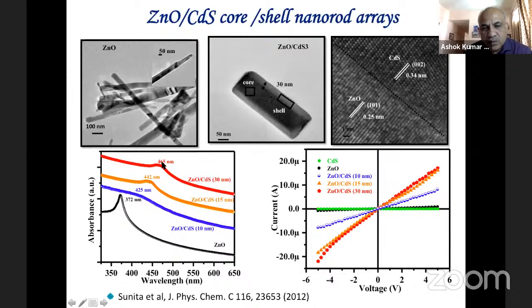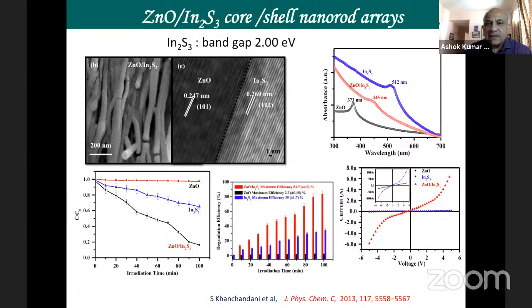So the band gap is shifting with the thickness of the shell. From UV, it goes to the red, from 372 towards 465. And you can see the photocurrent increases. The red plot has a higher photocurrent for the same voltage compared to the blue, and so on. So we can show that the design of the photocatalyst works, and you have a higher efficiency with appropriate shell thickness. A similar thing can be extended to indium sulfide. Earlier we saw cadmium sulfide shell on zinc oxide. Now we have indium sulfide.